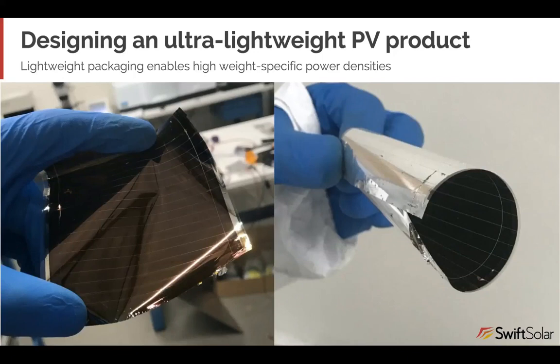So we've been heading in that direction, designing very lightweight PV products based on these perovskites. These pictures are for single junctions, but certainly you could do the same thing for tandems. And a key piece of this is making a lightweight package. Because the substrate and the packaging dominate the weight, you need very lightweight packages with good barrier properties to make these very high watts per kilogram products. You can see they're obviously very flexible as well.